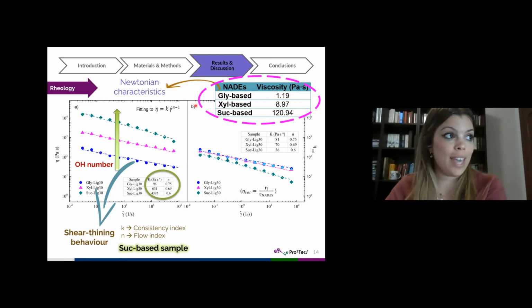As expected, the higher consistency index was obtained for the formulation prepared with sucrose, which also exhibits a slightly more enhanced shear thinning character. I mean, these values were higher.